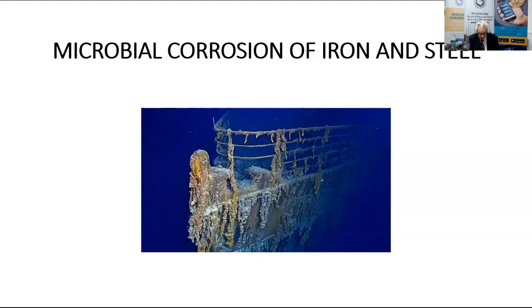MIC is caused by specific genera of bacteria which feed on nutrients and other elements found in the water. Sea and canal waters are a primary source of sulfate-reducing bacteria, or SRB. The biological activities modify the local chemistry, producing acid, and render it more corrosive to the metals. For example, iron-oxidizing bacteria can perforate a 5 millimetre thick AISI 316 stainless steel tank in just over a month. That's fast. I was also once told of a case where the bugs had eaten through a 12-inch, 300 millimetre thick piece of mild steel in a year. But sorry, I have no further information on it. It's amazing how bugs can work.